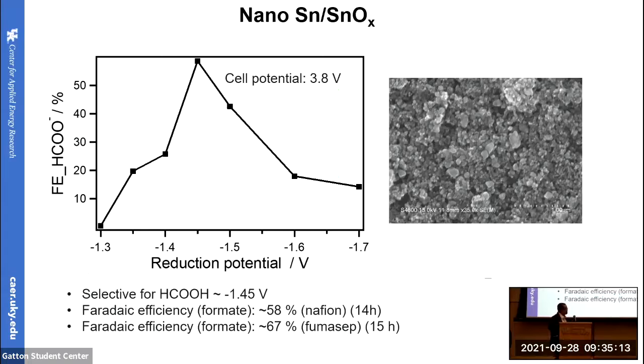This figure shows the morphology of the electrode, and this is the Faraday efficiency as a function of electrode potential. Here we got a peak Faraday efficiency at negative 1.45, which is 100 millivolts less than the copper one, and we got a Faraday efficiency of 58% in 14 hours. But this was using Nafion, a cation exchange membrane that separates cathode and anode. We got some issues with that, and we replaced it with a bipolar membrane, FumaSep, and with that we got 67% in 15 hours. That is very good for lab scale.